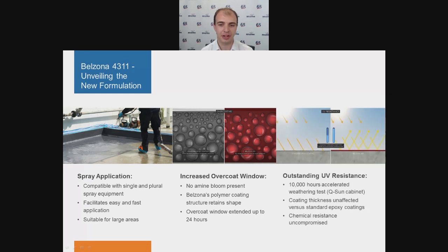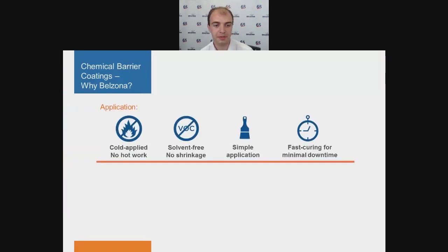Finally, we have the UV resistance of Belzona 4311, which has been enhanced even further. As we mentioned before, extensive testing is a priority for Belzona, and this coating was subjected to 10,000 hours in an accelerated weathering test, with the coating thickness barely affected. So in sunny climes where there are high levels of UV exposure, you can be assured that the chemical resistance of the coating will be uncompromised. Now I'm going to hand you back over to Tom just to give you a bit of a summary on the product benefits.